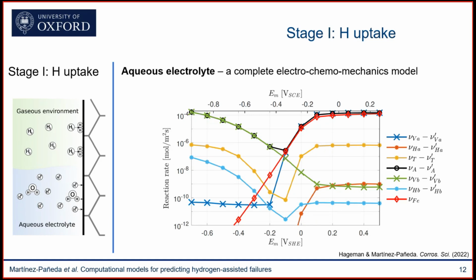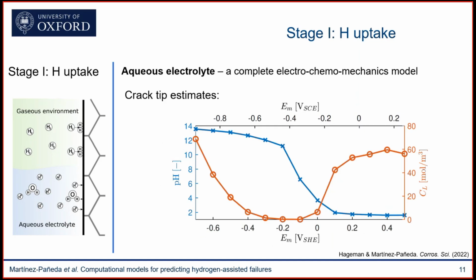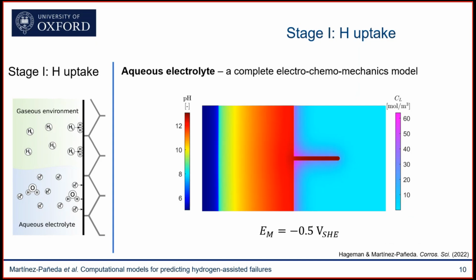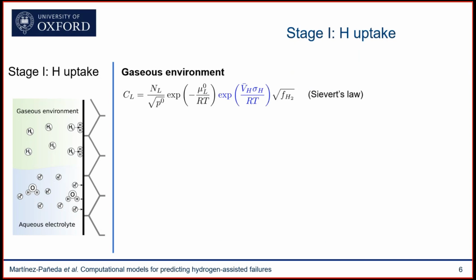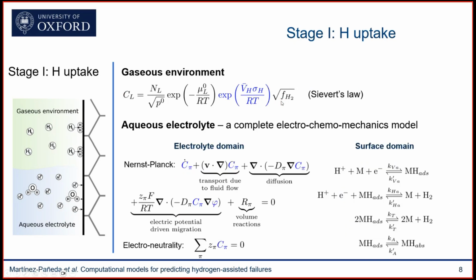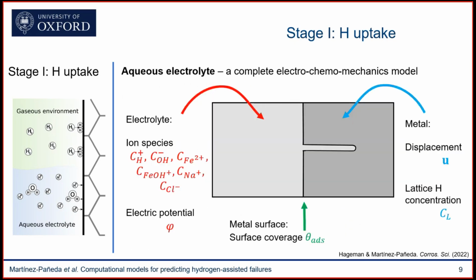But one other aspect that I would say is arguably even more important is that we can finally correlate gaseous environments with electrochemical environments, because we have a tool that allows us to predict the hydrogen concentration ahead of a crack for a given electrochemical environment. And then we just need to go back to Sieverts' law and say, okay, since we know the hydrogen concentration, we can solve for the pressure, and we know that this electrochemical environment is equivalent to testing metals in this other hydrogen gas pressure environment.